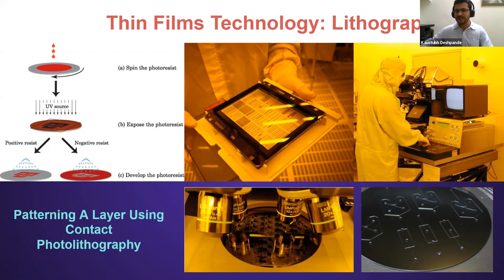And then this is called the mask aligner, contact mask aligner, which allows you to align features on the wafer to the next layer. And then with a UV source, you expose it. Just an image of how the wafer and the reticle align. And then finally, the photoresist layer gets developed to make features on it. So eventually, you're finished with either putting down metal or taking away metal. You can then dissolve this photosensitive layer away, and then just have the metal or the etched portions remaining.